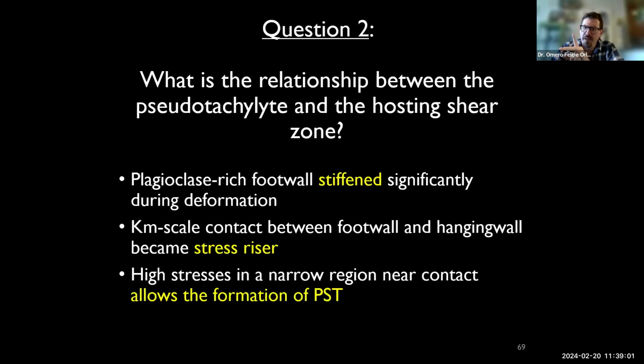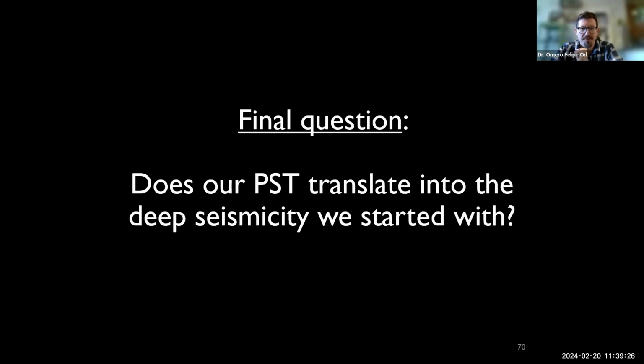I think that major lithological contrast in our shear zone ends up being a really, really important thing to think about for why we end up with the patterns of stress and grain size and deformation mechanisms we see in the shear zone. And I think that allows the formation of pseudotachylite in otherwise a very, very hot, very deep ductile environment that should not allow brittle failure at all. But this creates the conditions necessary for you to get these brittle failures.